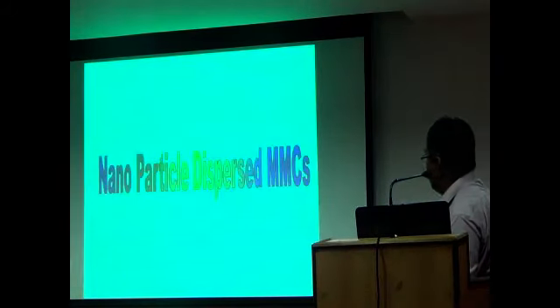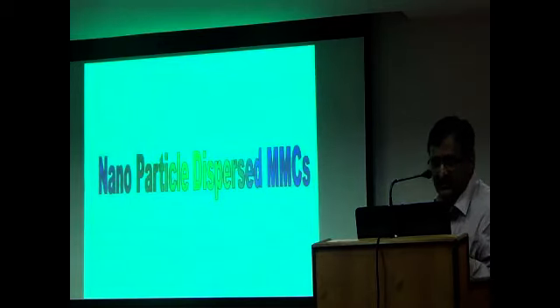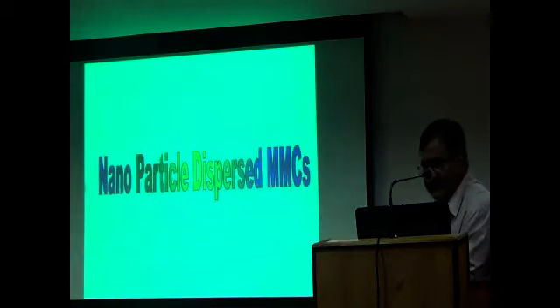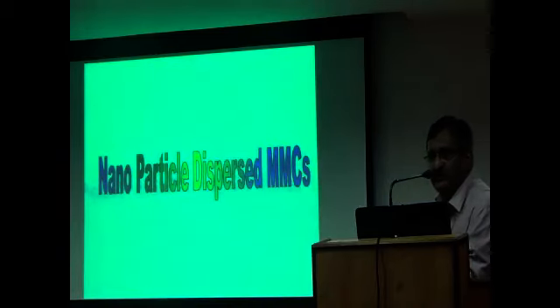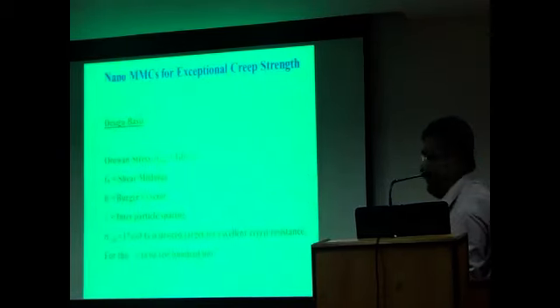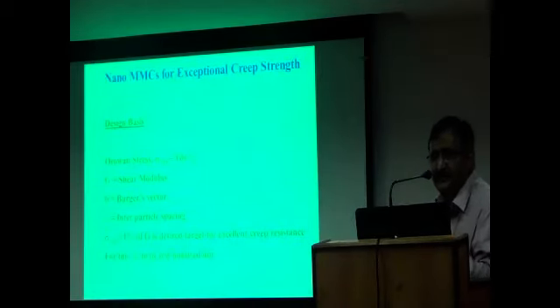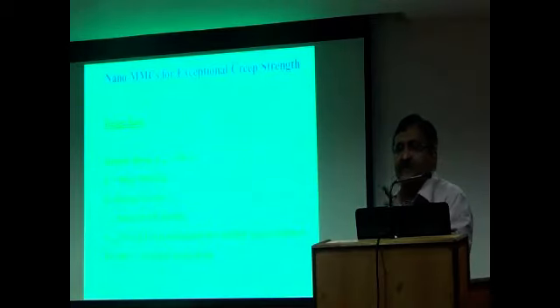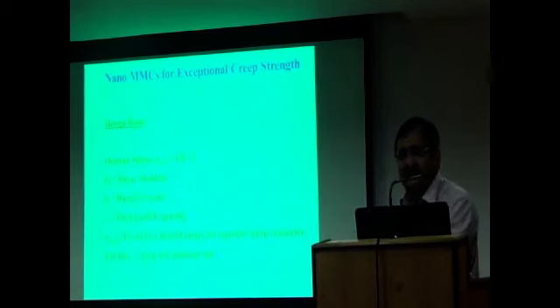Anyway. Now coming to the most recent work, which is also of interest, on the nanoparticle dispersed composites. The reason why we went ahead and thought about the nanoparticle is the basis for it. In general, if you use any aluminum, any metallic material, only a fraction of the shear modulus is the strength, because of the easy movement of the dislocations, plasticity and all. It is less than 0.1%, 0.2%. That is the strength as a percent of the shear modulus of any given material.